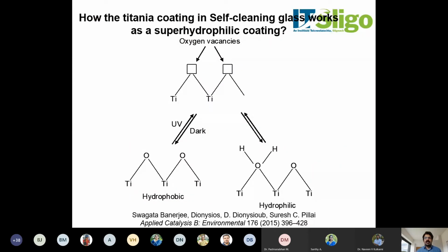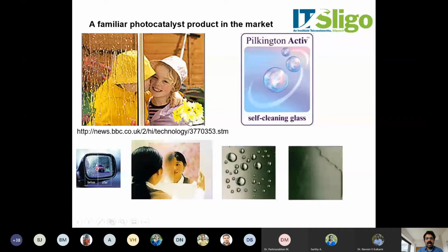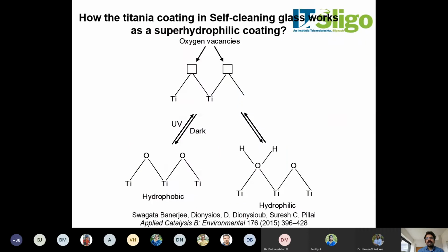So how does this work? Most of us are chemists, so we need to understand what is going on there. How is a hydrophobic surface changed to a hydrophilic surface? A semiconductor material is coated on this surface, and mainly these materials are TiO2, or titanium dioxide. When light hits titanium dioxide, an electron moves from its lower energy level, which is the valence band, to the conduction band. When some of the electrons are moved from the valence band to the conduction band, Ti is in the 4+ state, Ti4+, so the oxidation state Ti4+ will change to Ti3+ for some of the titanium on the surface. In order to keep the stoichiometry, some of the oxygens have to move from the surface, which means a number of oxygen vacancies will be created on the surface.